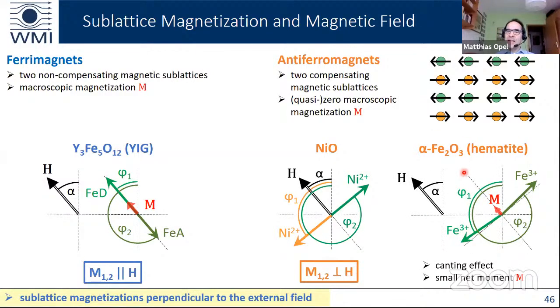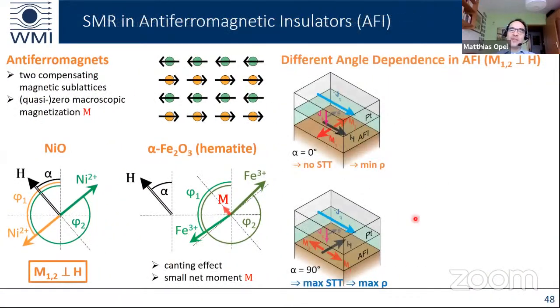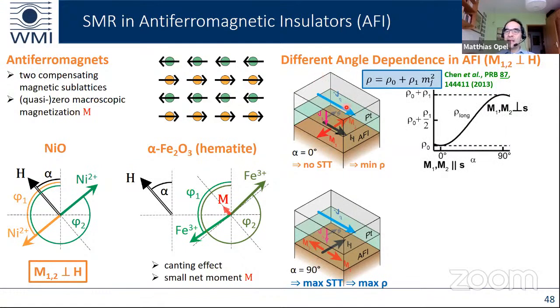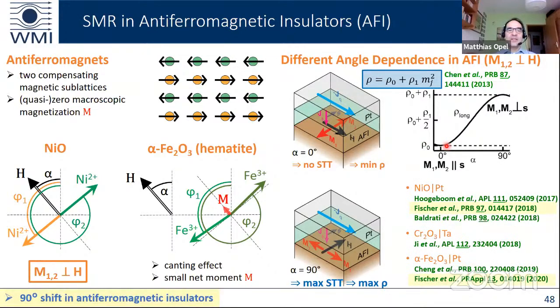The same is true for the hematite, with the small difference that we have a small canting angle between these iron sublattices in hematite with a small net magnetic moment. But also here, the magnetic sublattices point more or less perpendicular to the external magnetic field H. And when we now apply a magnetic field to a double layer structure of platinum with an antiferromagnet, we find that the magnetic sublattices are pointing perpendicular to the external magnetic field. When we rotate this magnetic field and again observe the resistivity of the platinum, we again find this oscillation, but the oscillation is shifted by 90 degrees with respect to the earlier experiments in the ferromagnets. So this was first shown in nickel oxide platinum and also in chromium oxide tantalum, and then in hematite platinum in these publications.